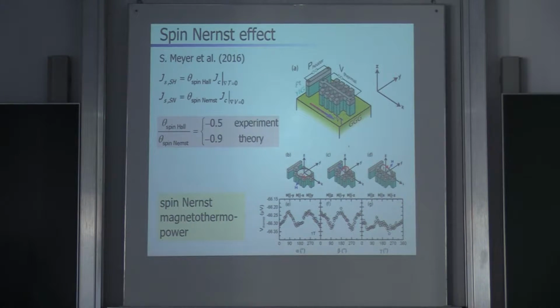Now, how can you measure that? This is the structure here. It is a Hall bar structure of a platinum film on top of YIG again. On the left side, you see there is a heater. By driving a current through this one here, it gets hot. Then there will be a temperature difference between this contact and this contact. This means there is a heat current, and if you have thermoelectric effects, a charge current is also flowing from here to here. And these are Hall bars, which can measure the Hall effect if you like,